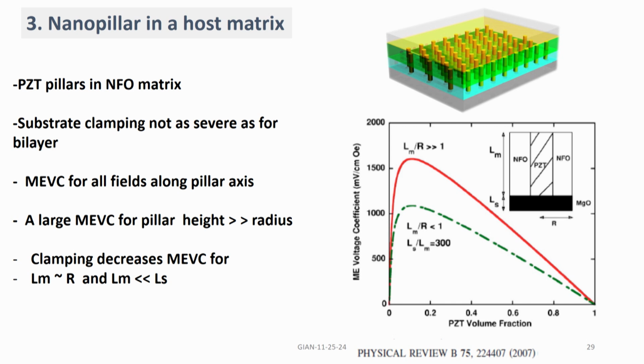Now, when the substrate radius is much smaller than the length of the nano pillar, the clamping is rather weak, but when it is comparable, there is significant reduction in the magnetoelectric coefficient because of the clamping effect.